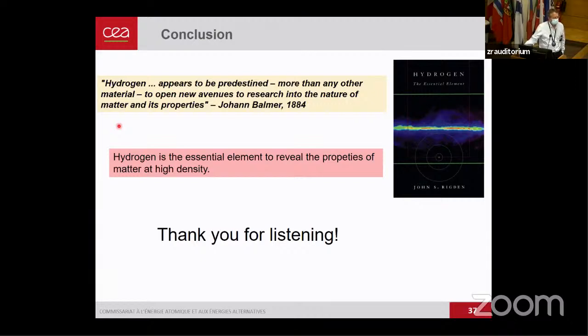We have a question from John Eggert. You showed that the diamond absorbs strongly in the visible above 450 GPa. Have you measured diamond absorption in the infrared at these pressures? Yeah, good question. This is ongoing. We have an experiment that will be going. If you want to probe to really close the gap, you have to go above 500 GPa, and this is what we are planning to do. Not yet, but it has to be done.